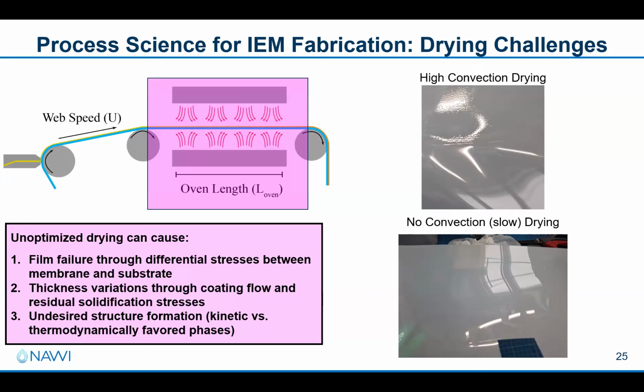And then if we look at changes in drying conditions, where say we switch to slower drying under hot air, this stress development is slowed down. Enough time is given for the polymer chains in this material to relax, and for stresses to dissipate. And as a result, you can get a smooth coating, which is a smooth coating on top of a transparent material. So it comes off as just somewhat reflective.